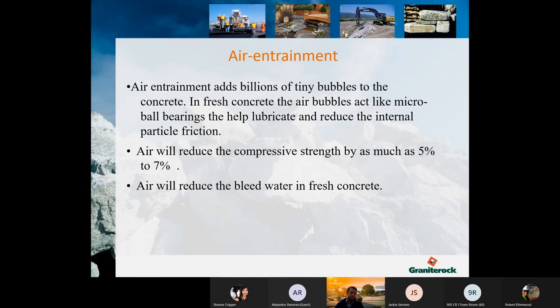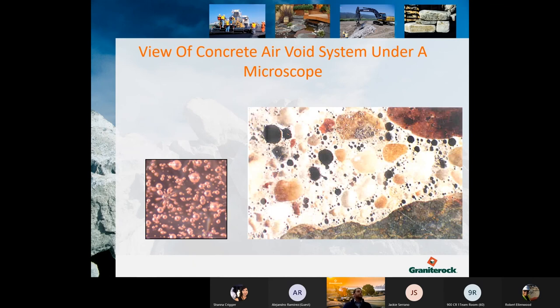And the reason why air entrainment helps there is the moisture in the concrete, when it freezes, expands, and all that pressure is enough to break apart the concrete. The air bubbles give basically a cushion where the frozen moisture can expand without breaking apart the concrete. Like I said, here we don't have too much of that, luckily. Here's a close-up look of the bubbles created from the air entrainment. Now we're talking about air entrainment, but there's also air entrapment, which is just due to normal mixing. So the larger bubbles here are most likely that. However, the smaller tiny black dots on this picture here are the bubbles. And this is also in the cement paste where this happens.